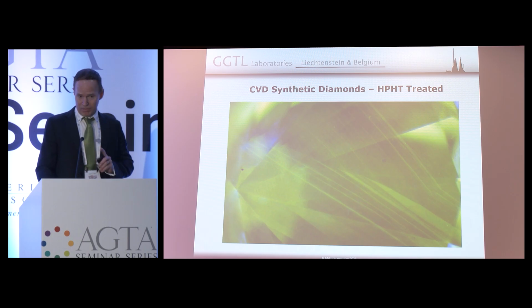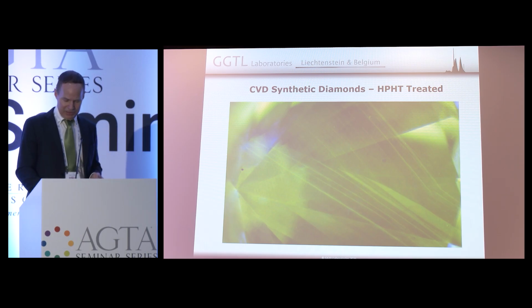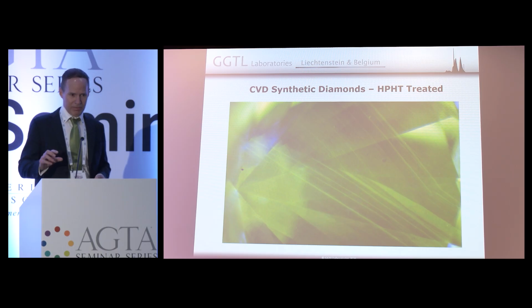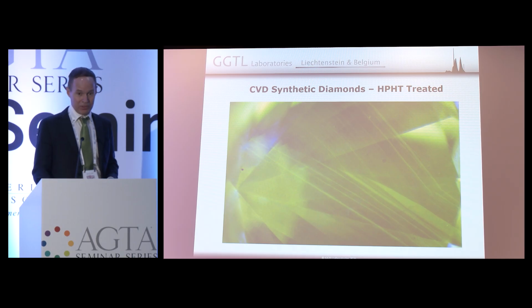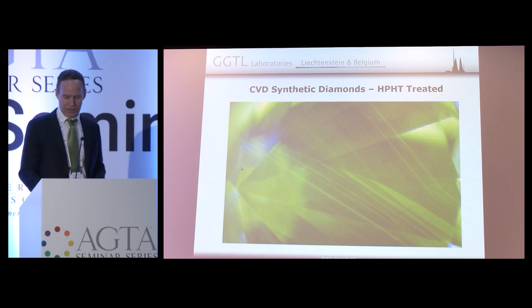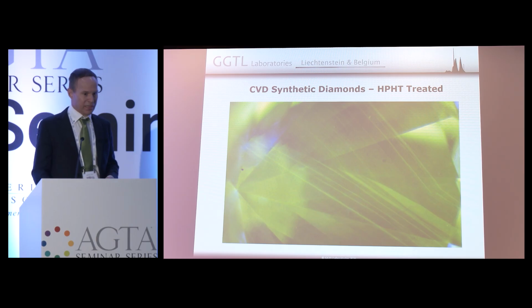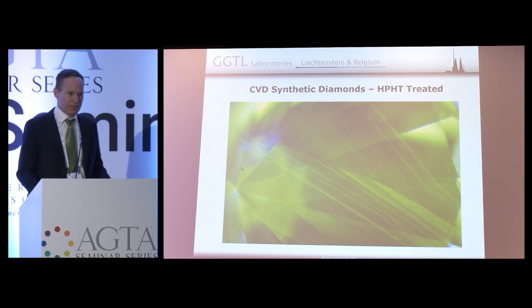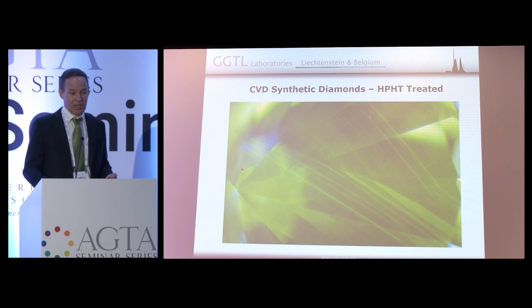HPHT-treated synthetics, I mention it separately because it's a very common thing in the market. Much of the CVD material is grown very fast, therefore is very defective, therefore is brownish. So this brownish color has a similar origin like in natural diamonds. The brown color, you can get rid of it by HPHT treatment. And the HPHT treatment of CVD diamonds makes them colorless and completely changes their fluorescence properties.